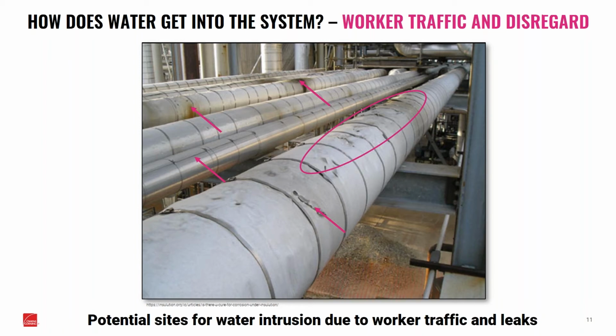But I think more telling is this pipe that's closer to us, the larger one. You see the large oval and that bottom arrow. You can see that there's actually cuts in that jacketing. And earlier I was talking about the Owens jacketing that you have over a heavier insulation. Well, this is the reason why that thinking doesn't work here, is because this jacketing is supposed to be protecting the insulation. Clearly, there's been some kind of traffic or damage or something that's happened here. So now we've created all these entry points for moisture to get in. So again, this is either worker traffic or just disregard for this entire system. So there's a lot of potential sites for moisture to get in.